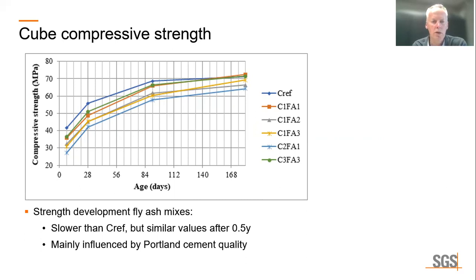a slower strength development than the reference concrete, but reach similar strengths after half a year. And within the fly ash mixes, we can see that the strength development is mainly influenced by the Portland cement quality.